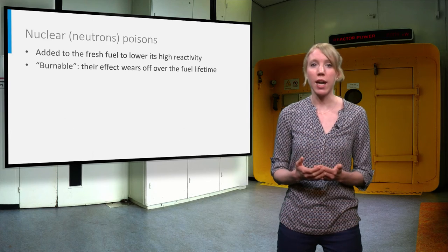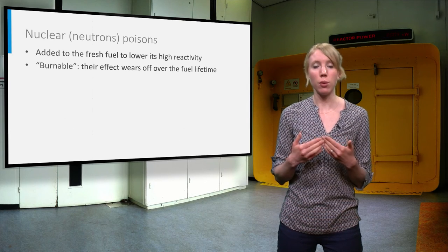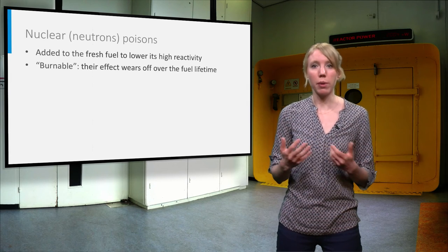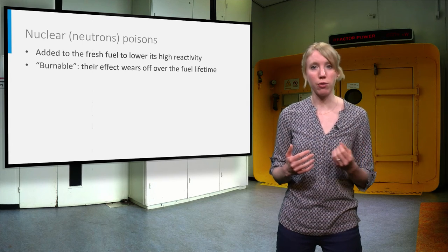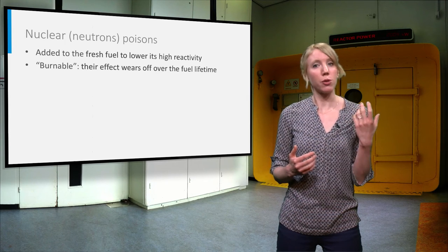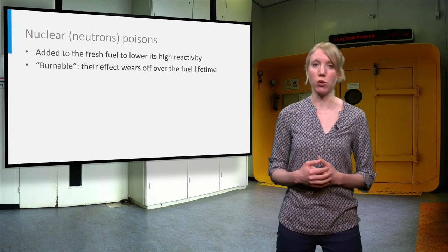The neutron poisons are added to the fresh fuel to lower its high reactivity. They are called burnable because their effect wears off over time as they transform into a form that absorbs very little after capturing a neutron.